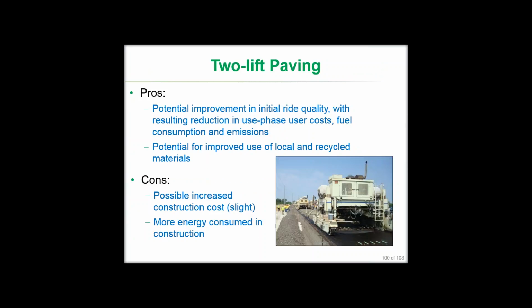Two-lift paving, again, you've seen this before. I think one of the things we often forget about is that when we construct the pavement in two lifts and you're putting down 7, 8, 9 inches of the lower lift of concrete, you've established a profile there with that, and placing the second lift on top, particularly if it's following by 20 or 30 minutes behind and that lower lift has started to kind of stiffen a little bit, makes for a very good construction platform, and the